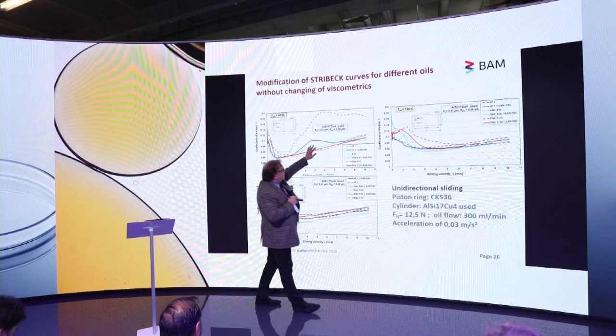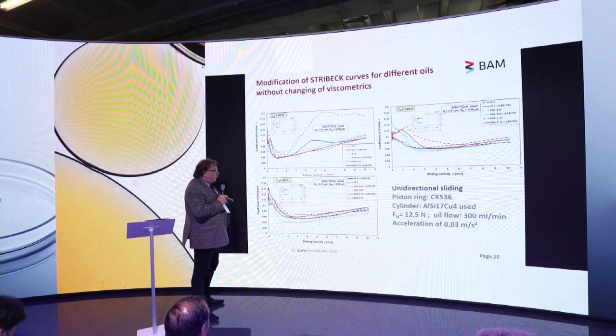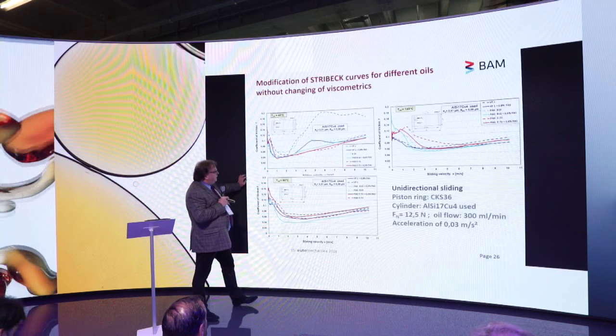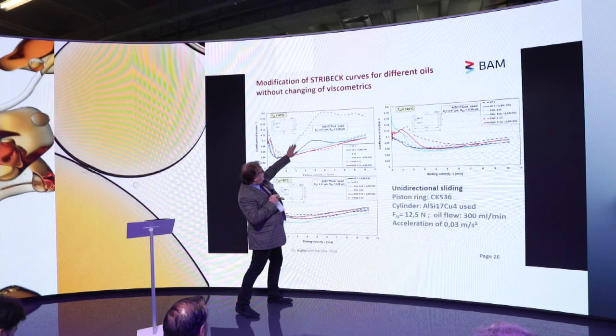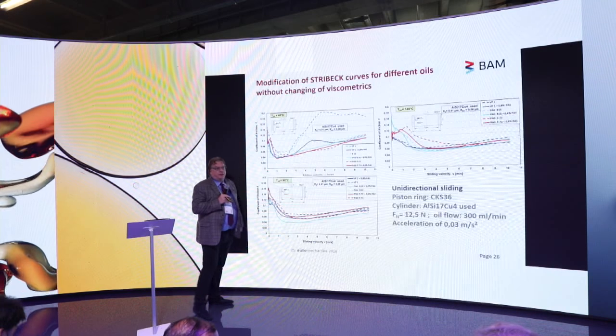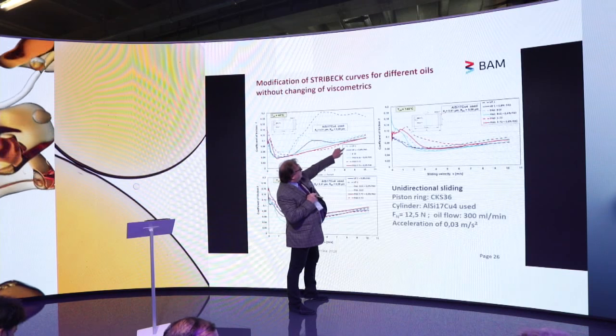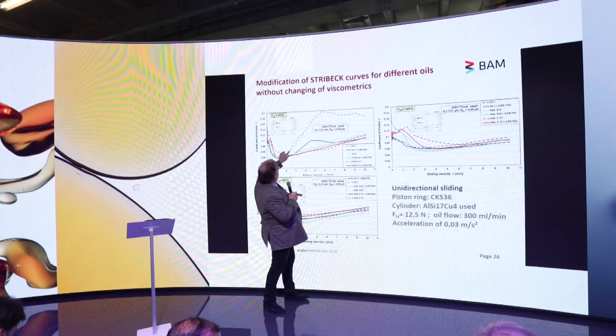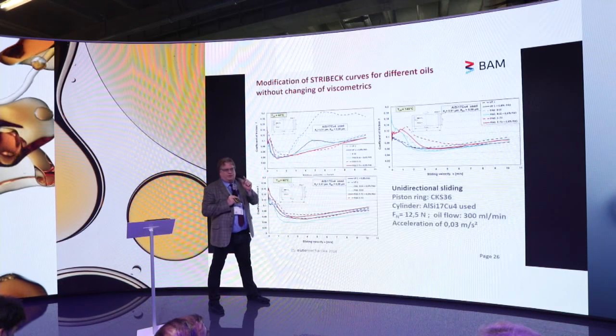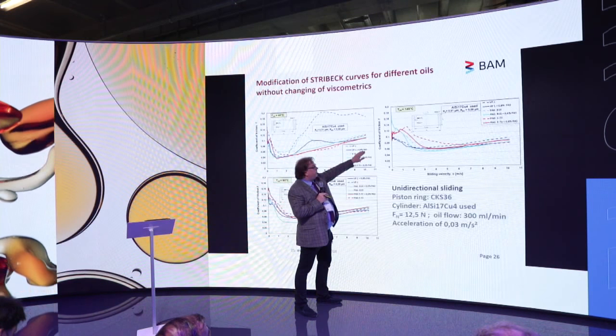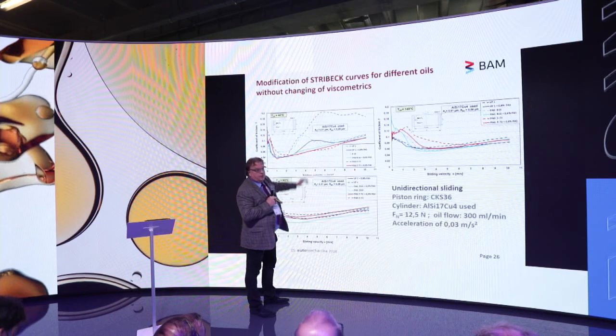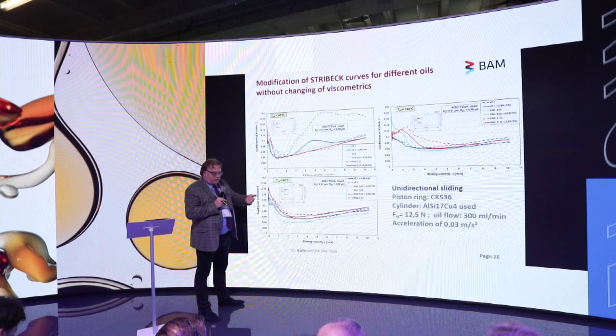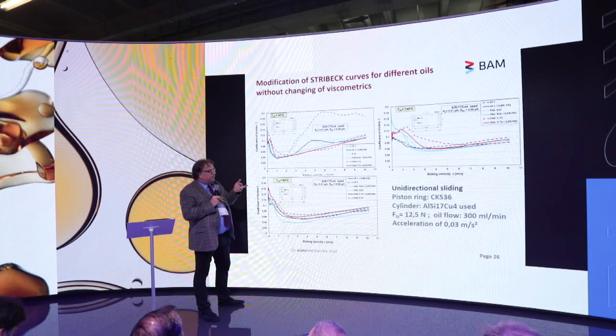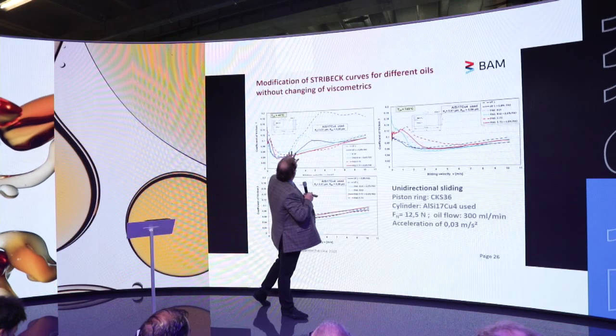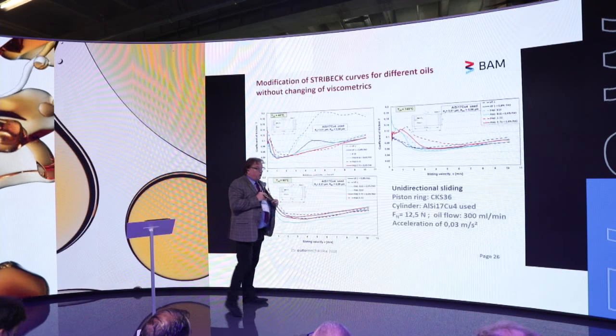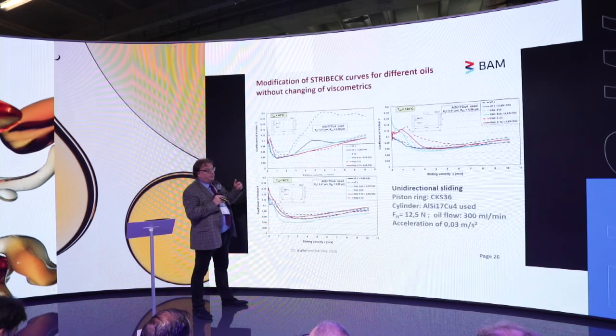Same for an aluminum liner. Aluminum silicon 17 copper 4 is a typical aluminum liner, and here you see the same. At room temperature, high friction, and changing the chemistry, it goes down. But look here, this is a factory fill oil, quite high friction. Now, without changing the viscosity, you put in an additive and suddenly friction is down. So you can use new base oils, low viscosity base oil, or chemistry to reduce friction. At 40 centigrade, at higher temperatures, you always have the same effect with this additive in hydrocarbon and in the polyglycol.